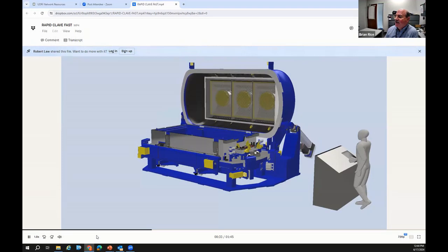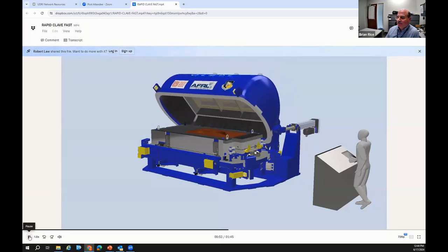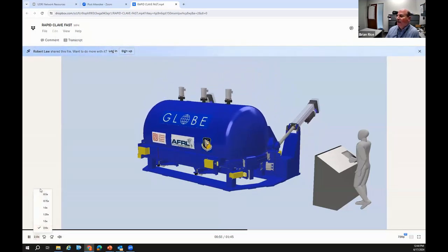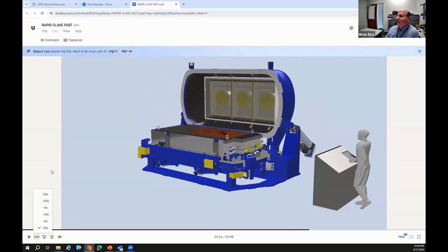So that way we can achieve rapid cure cycles. As you can see, it's split down the side to make it easier to automate the part placement and extraction from the rapid clave. So what you're seeing there is on the base over here on the right-hand side where my cursor is, all the process utilities get plugged in automatically, including thermocouple ports, vacuum ports, etc. So it's really designed to operate much more quickly and efficiently and in more of an automated mode than, say, an autoclave would be today. Kind of speed up there a little bit. So you can see how the clamping mechanism operates for the pressure vessel and how the door opens and closes and the tool gets placed in and extracted.